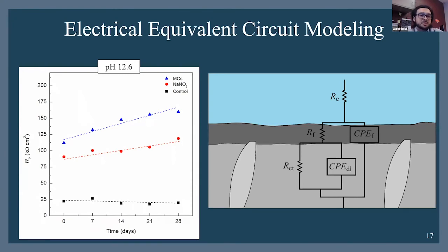And on the left are calculated Rp values from the EIS for the simulated concrete pore solution, as that is the major focus, to see that over a 30-day period, the polarization resistance values of the microcapsules are even higher than our free inhibitors, even with comparable nitrite concentrations, likely also attributed to any effects of the colophony, as well as the release of the corrosion inhibitors themselves.